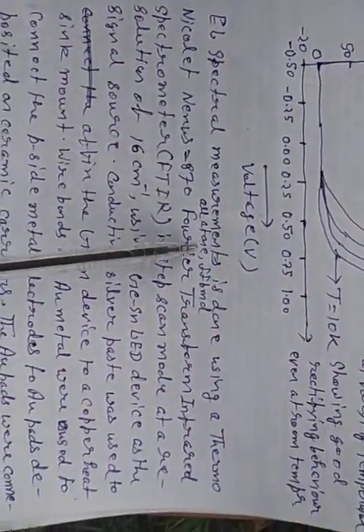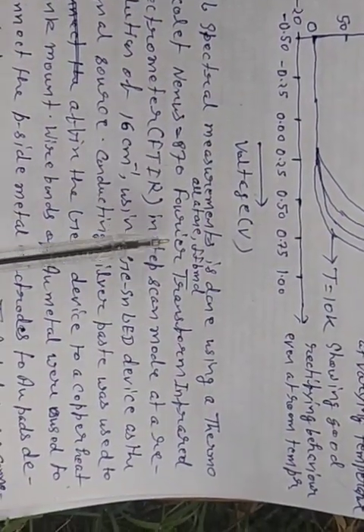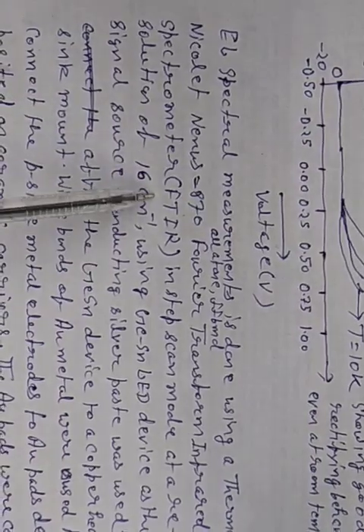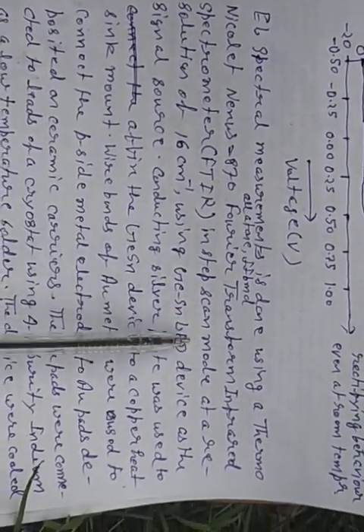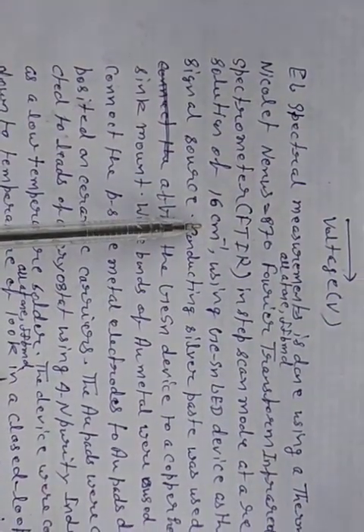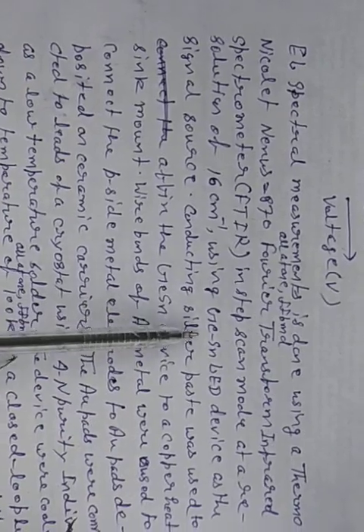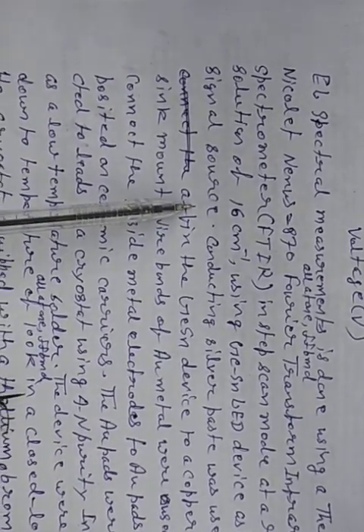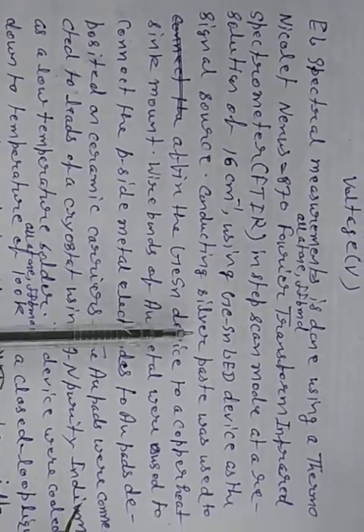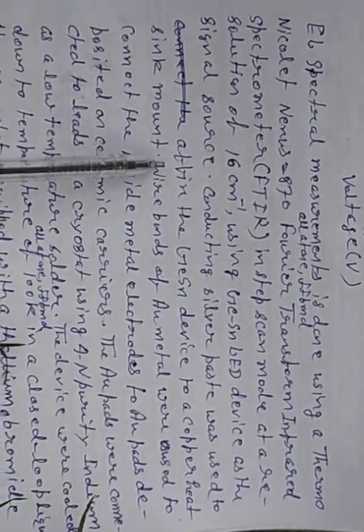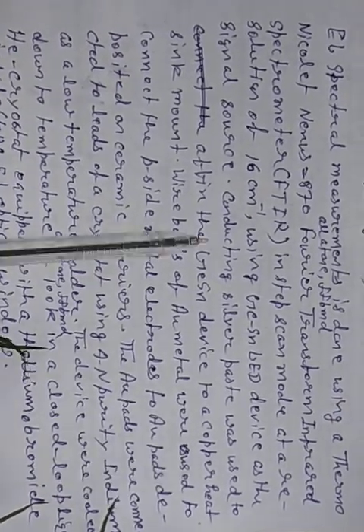Electroluminescence spectral measurement is done using a Thermo Nicolet Nexus 870 Fourier transform infrared spectrometer (FTIR) in step scan mode at a resolution of 16 per centimeter, using the GeSn LED device as the signal source. Conducting silver paste was used to affix the GeSn device to a copper heat sink mount.